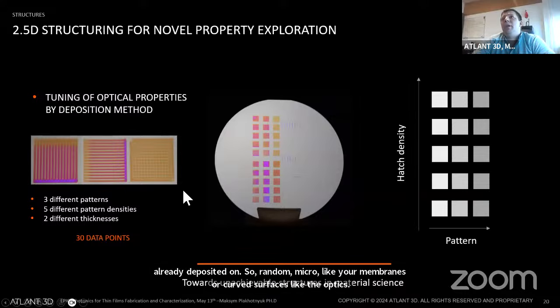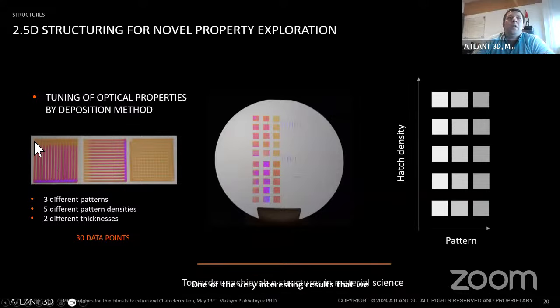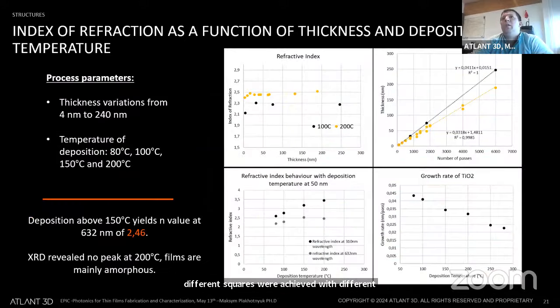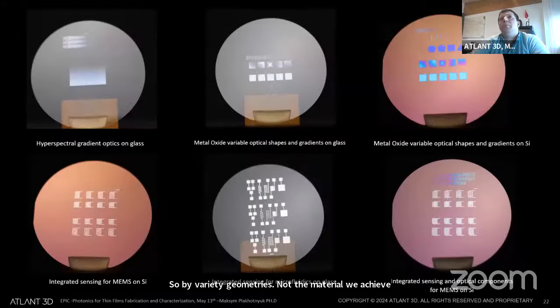One of the very interesting results that we recently obtained is by printing variable vertical, horizontal lines, we obtained the squares, as you could see here. And by varying different thicknesses, you could see different squares were achieved with different geometries. And the next, what we did, we tested this to basically modulate refractive index. So by varying geometries, not the material, we achieve different refractive index changes. So this is just overview to give you an idea what we did recently.